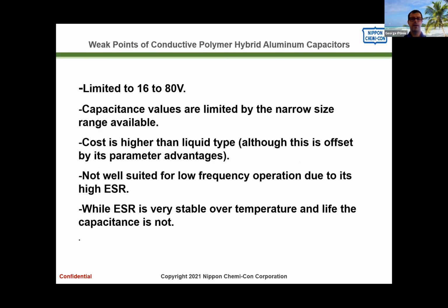Disadvantages or weak points: it's limited basically up to 80 volts, 16 to 80 volts or so for now. Capacitance values are limited by the narrow size available. The biggest size available is 10 by 16 millimeters. So invariably, because of that, you're going to have a significantly lower capacitance. Technically speaking, we can make higher capacitance versions or larger size versions for hybrids also. Same is true for polymers. But the market need is not really there when you take into account the voltage range.